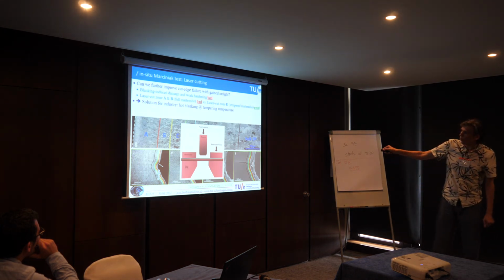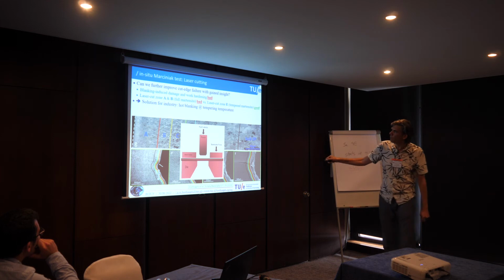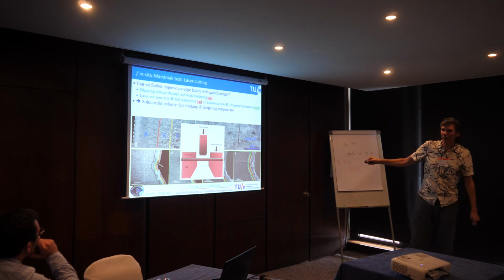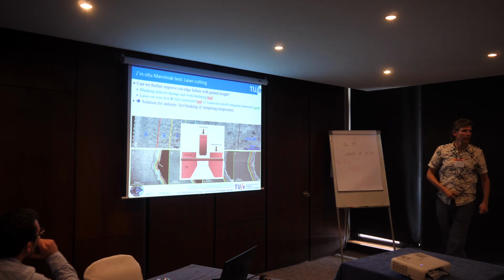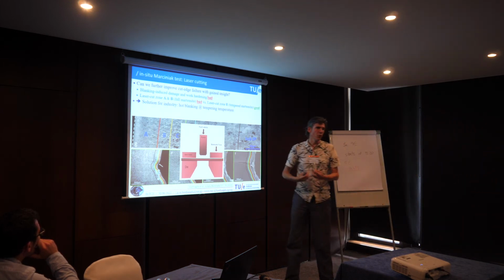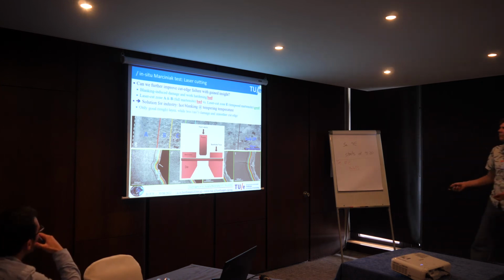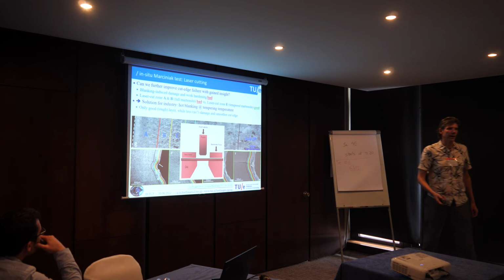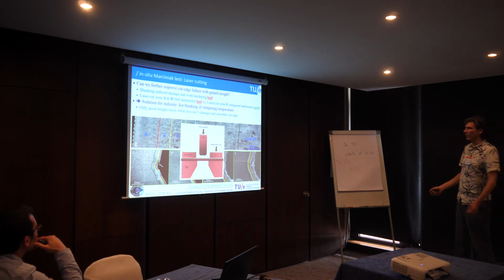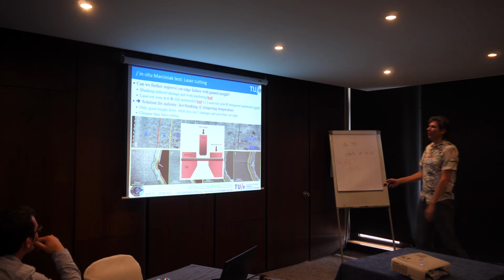because it's much cheaper. So the solution that we reach from this is that we should actually do hot blanking. Hot blanking at a temperature that induces this kind of toughening mechanism. And because of that high temperature, we will also induce less deformation and damage into the material. And this is something that I'm now trying out. I can't say anything about this yet. Okay, that's our suggestion.